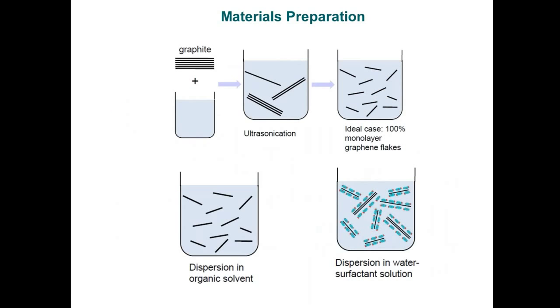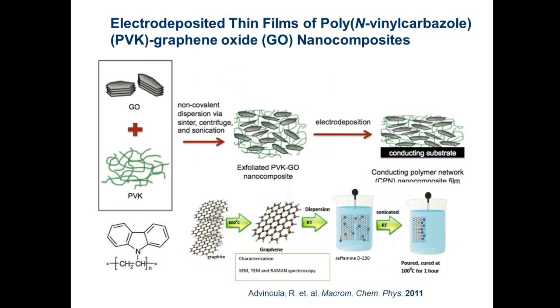As you can see here, graphite, when sonicated, can be broken into monolayer graphene flakes, which can be dispersed in organic solvents. Graphene oxide is actually very well dispersed in aqueous solvents, and to transfer them to organic or more nonpolar solvents requires a bit of complexation and modification, such as using surfactants to aid their dissolution in a variety of solvents.